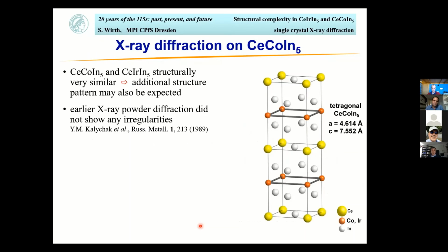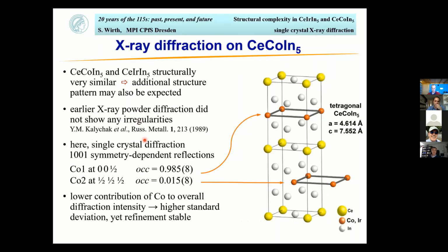Now, if we think about CeCoIn5 and CeIrIn5, the two of them are structurally very similar. So you could expect a similar pattern. This was not indicated by earlier X-ray powder diffraction experiments, but when we did our elaborate experiments, we could see that again we found something like 1.5% of the cobalt in this additional structural pattern. I should point out that here we have a lower contribution of the cobalt to the overall diffraction intensity, and therefore the standard deviation is a little bit higher. Nonetheless, the refinement worked stable.